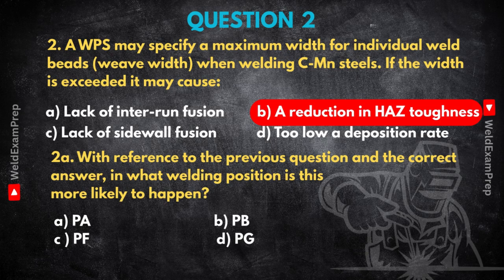It's generally going to be C, PF, vertical up. Vertical up. Why there specifically? Well, think about it. Welding uphill, you're fighting gravity constantly, right? Gravity wants to pull that molten weld puddle straight down. So to counteract that, to control the puddle, stop it sagging, fill the joint properly without getting undercut, welders often have to use a wider side-to-side motion, a wider weave or oscillation. It helps them manage the molten metal.